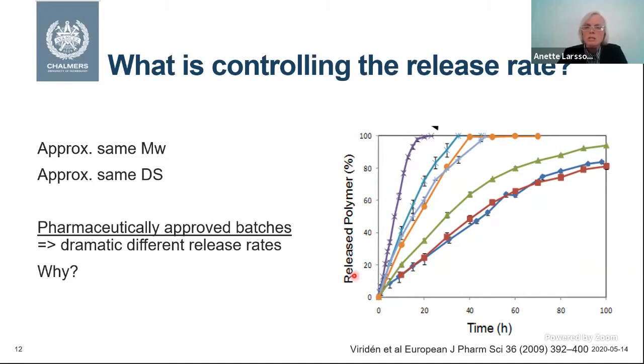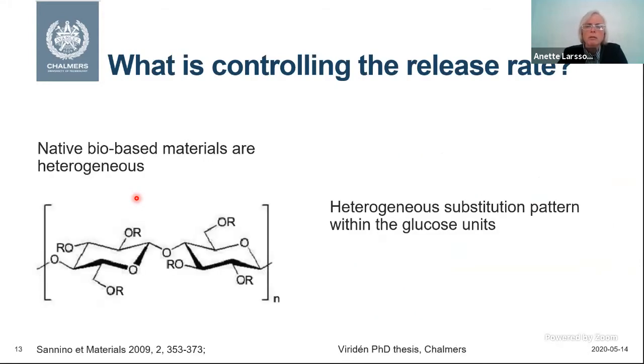That is the thinking behind it. So this is nothing else, it's just a polymer, and you can see that this polymer is eroded away after 20 hours, and here it's not eroded away even after 100 hours. And we investigated these 7 different batches, and we could see that they had the same molecular weight and the same degree of substitution, which then makes you question, why does this happen? So we continued to look and think about it.